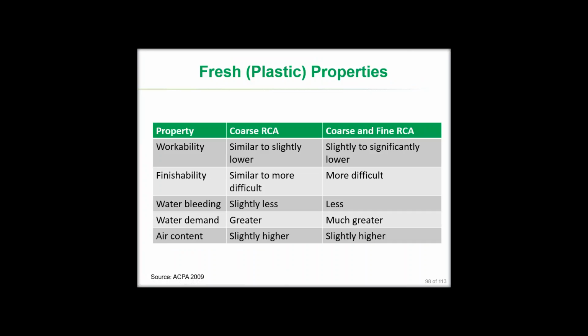There's a general description in the text and also in the ACPA resource on the impact of using crushed concrete in new concrete mixtures, the impact on the plastic properties, the workability, the finishability, the bleeding, and water demand and air content. And they vary depending upon whether you're using just coarse crushed concrete, which is the usual approach, or coarse along with some fine crushed concrete. And we are seeing a movement towards people using maybe between 15 and 30% fines as a replacement for natural fines in some of these mixes, because A, it's a place to use the material, and B, it actually seems to be somewhat beneficial in terms of the strengths that result. It kind of fills in a gradation that's often missing between our coarse aggregate productions and our fine aggregate productions, so it's of some use there.